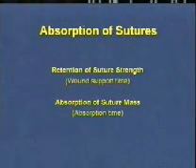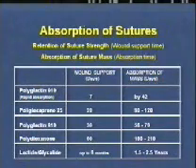Synthetic absorbable sutures are hydrolyzed, a process by which water gradually penetrates the suture filaments, causing the breakdown of the suture's polymer chain. This process means that the loss of tensile strength and the rate of absorption are separate phenomena, which are clearly demonstrated by the figures in the chart. A suture can have lost all its tensile strength and the tissue have healed, but potential adverse reactions are still possible until all the material has completely disappeared. It is therefore important to be aware of the time taken for the suture mass to be absorbed.